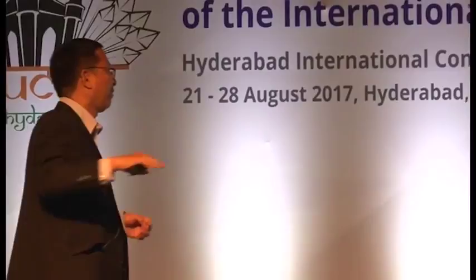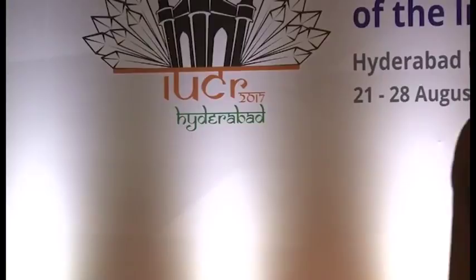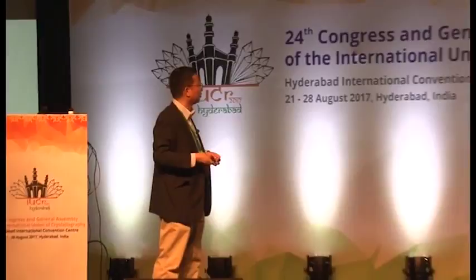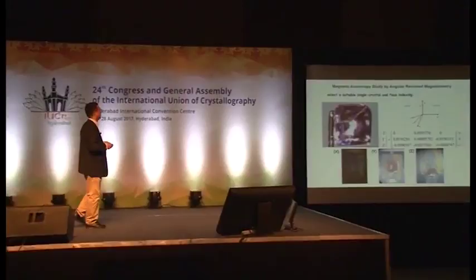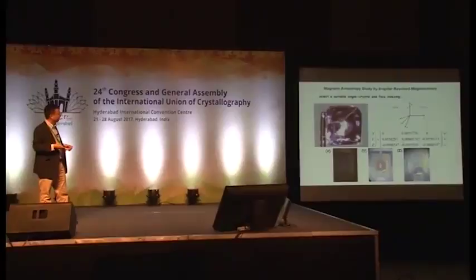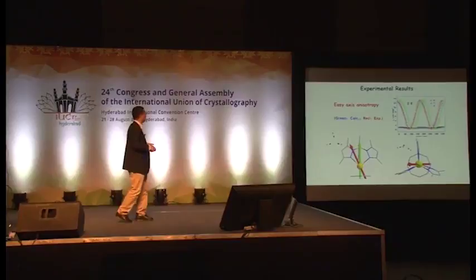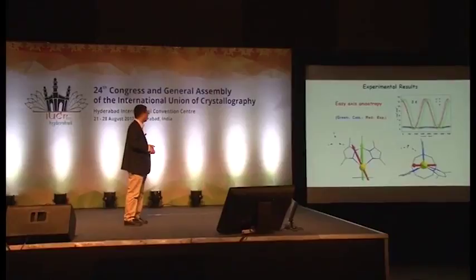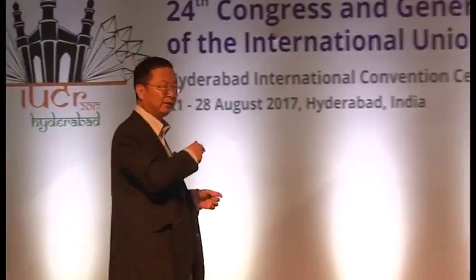It's possible to replace the Cp* with other ligands. Here we get a series of half sandwich compounds. For example, Cp* replaced by Tp*. For these compounds, fortunately, we also get a single crystal with this space group. So we can measure using an angular resolved magnetometer to determine the easy axis for the molecules. The green one is based on calculation, and the red one is determined by this single crystal measurement.